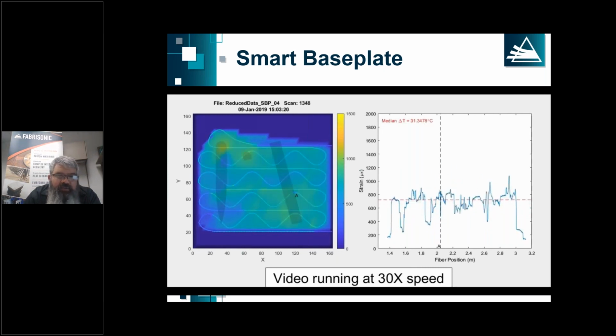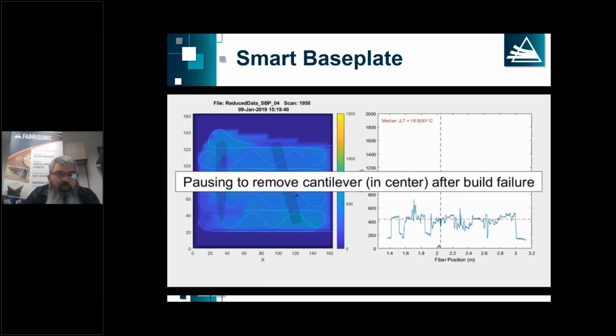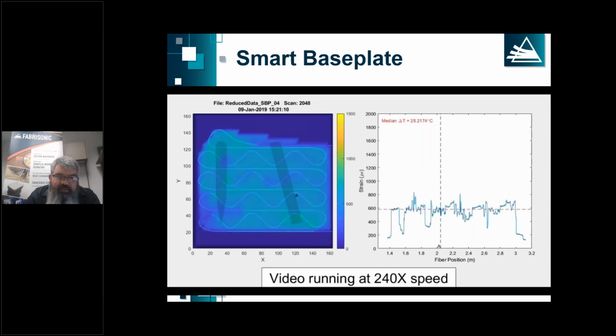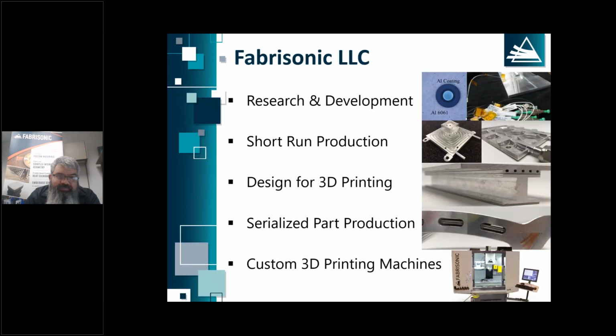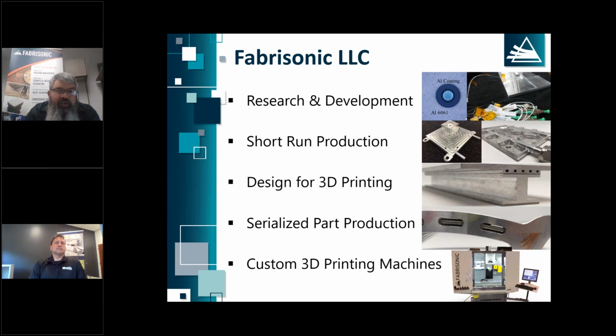And what we found is, magnitude is interesting, but the vector really pulls out if you have a defect forming in a powder bed build. If your strain vector at one point quickly changes by 70 or 80 degrees, something's happened from a strain state. So we're doing a lot of work on quality analysis and in-process build monitoring. But I just wanted to give a shout out since there's a lot of powder bed people out there. So with that, I think I will open it up for questions. Again, ultrasonic additive, at Fabrisonic, we do research and development, short run production, serialized parts, as well as sell these machines.